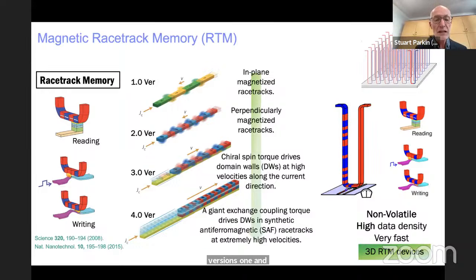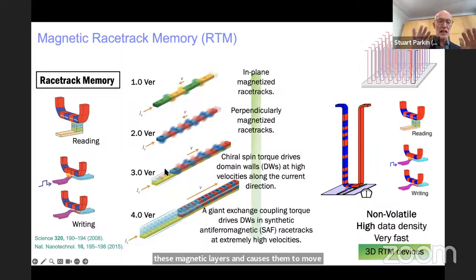And this is because in the platinum layer shown as yellow, the current is transformed into an orthogonal transverse spin current that diffuses into these magnetic layers and causes them to move at high speed. It only works because at the same time that platinum underlayer gives rise to a Dzyaloshinskii-Moriya exchange interaction that makes the domain walls chiral. And so the only reason why all the domain walls move in the same direction is this chirality. The chirality influences the direction in which the domain walls move for the same transverse spin current. This is the only reason why they move in the same direction. That's something we demonstrated and proposed.